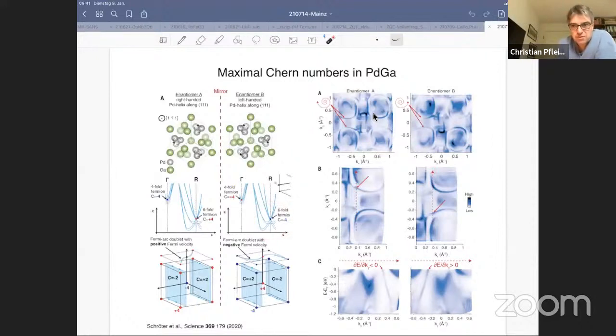this higher fold crossing at the gamma point on the one hand, and on the other hand, they could see the chirality, or demonstrate that you can switch the winding by going to the other chirality. This is, of course, a kind of switching that you don't do with a switch, but you just have to take the other crystal. But nonetheless, there's a certain element of control.